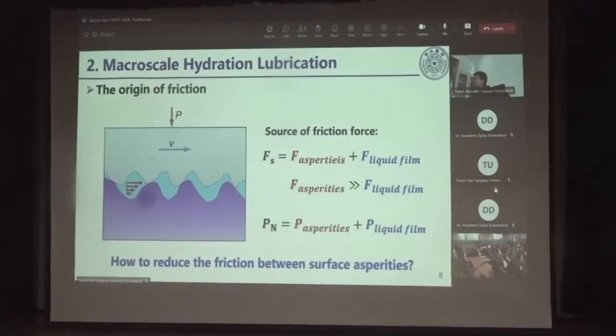First, as shown in this figure, for rough surfaces during sliding, the friction comes from two parts. First is the shear resistance between the contacted asperities, and the second is the shear resistance of the liquid film, as shown here. The force between the asperities is much larger than the shear resistance of the liquid film. So the key to achieving low friction is reducing the shear resistance between the asperities.